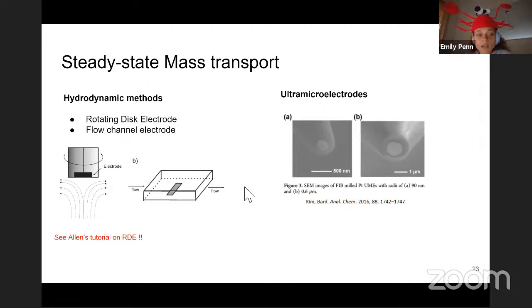So we previously discussed the case of planar electrodes that have semi-infinite linear diffusion. Those are larger electrodes. Ultramicroelectrodes are really small. Here in this paper, you see that the dimensions of the active surface of the electrode are very small. This one is about 1 micron. So when you have an electrode that's this small, you get a different diffusion profile, which allows us to obtain a steady state mass transport similar to what we see with a rotating disc electrode.